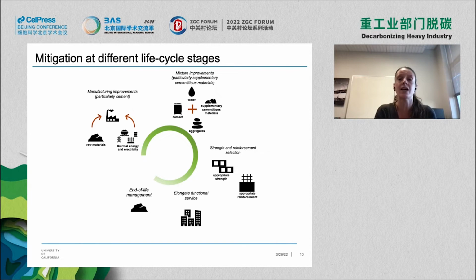We've also looked at things like how do we start to design better based on selecting an appropriate strength, selecting an appropriate reinforcement ratio. And actually, before I move on too much further from that, when I say lowering the cement content, I really mean lowering the clinker content, that solid precursor that has those high levels of greenhouse gas emissions associated with them. Some cements already have very low clinker content. So there's many potential areas that we could start to improve as we start to look at our design by, again, selecting the appropriate components as we're engineering. Elongating the use of our materials, as was mentioned by our previous speaker, can again potentially offset our demand for new materials. And at end of life, we could actually benefit from the fact that concrete can carbonate.